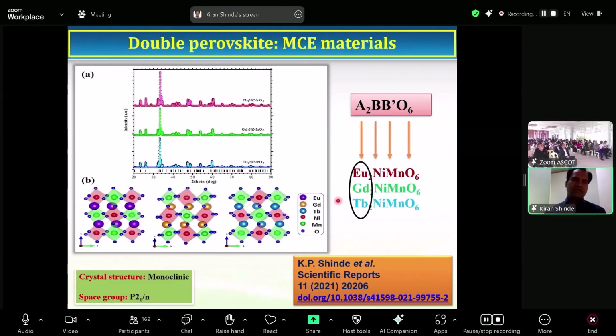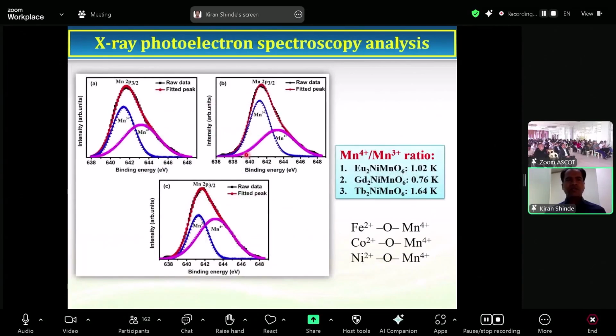So here we can see the X-ray diffraction pattern of these three different double perovskite compounds, and its crystal structure is monoclinic with space group P21/n, and these results were published in Scientific Reports in 2021. So as we know, manganese has different valence, so we confirm using X-ray photoelectron spectroscopy what kind of state of the manganese element is present in these different studied compounds. So we found that there is a variation of manganese 3+ and manganese 4+. So we check the ratio and we check how it affects the magnetic property of the double perovskite material.